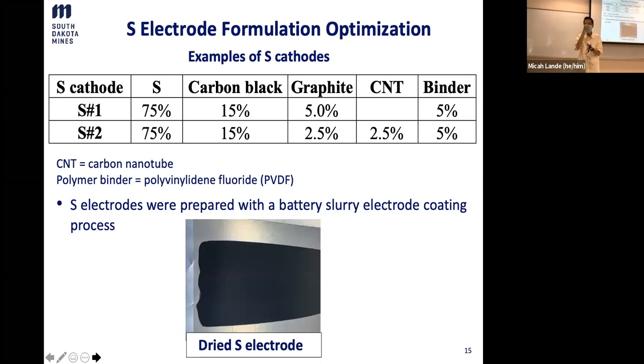Number two is, how do you balance the cell components? For example, when we do the laboratory work, we put a lot of extra electrolyte and lithium anode, just to study the cathode. But for the real application, you want to minimize the lithium as well, and the electrolyte. When you do that in a more realistic way, the performance actually deteriorates faster than when you use a lot of extra material. So those are the practical issues that we need to overcome.